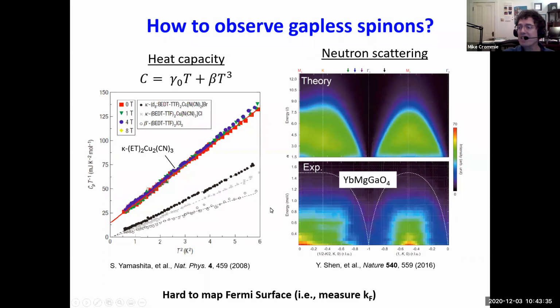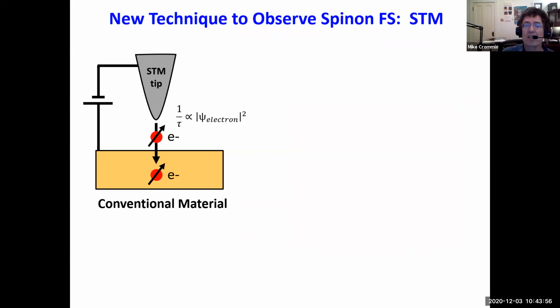But one of the quantities that's hard to observe is the Fermi surface. It's hard to map the Fermi surface of the spinons because we cannot use familiar techniques such as the Shubnikov-de Haas or de Haas-van Alphen effect. We cannot do that because there's no charge to the spinons. And so today what I want to do is tell you about a new technique that we can use to observe the spinon Fermi surface, which is scanning tunneling microscopy.